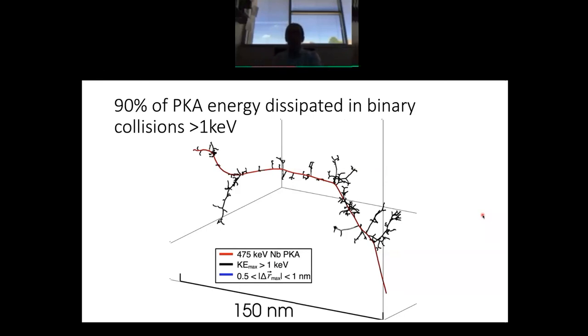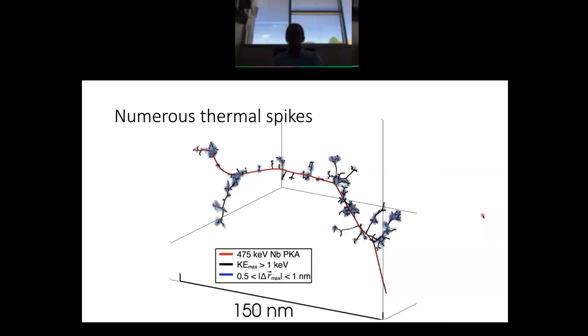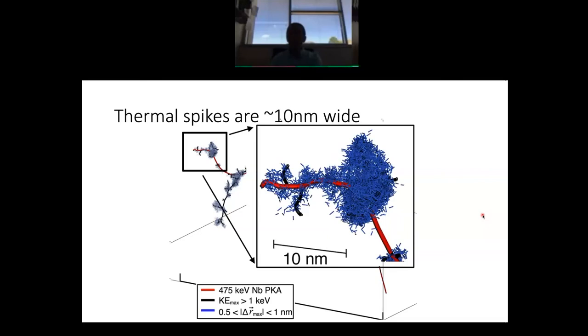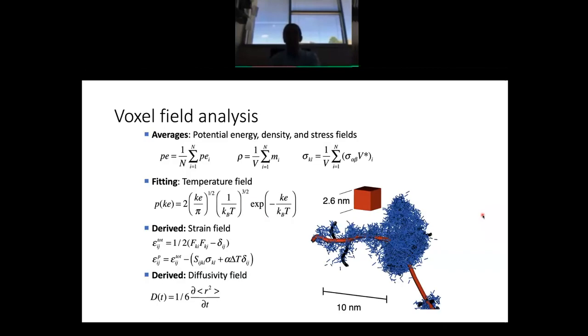That primary knock-on atom actually dissipated 90% of its energy in collisions that were 1 kiloelectron volt or above. Each one of these little sub-collisions that came off of the primary knock-on atom generated thermal spikes, so we got numerous thermal spikes in this model. If we look at one of those thermal spikes in detail, they're typically about 10 nanometers wide, or 10 nanometers in diameter. And we can look in detail at exactly what's going on inside each of these thermal spikes.